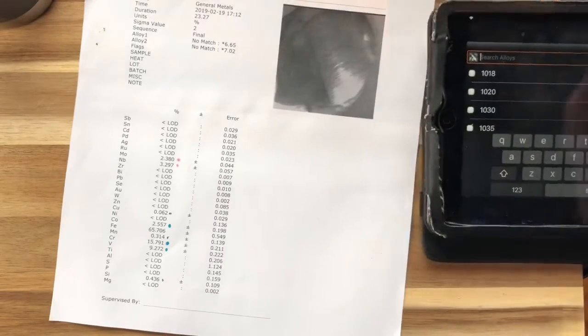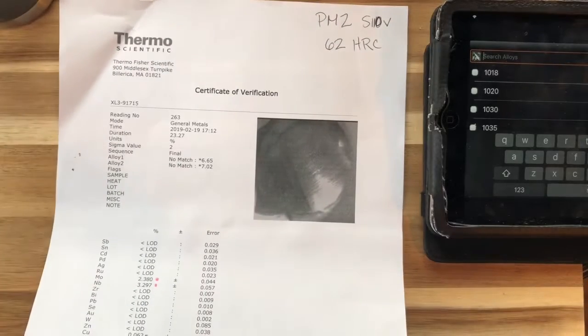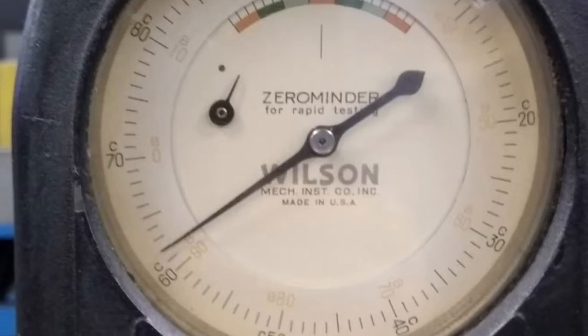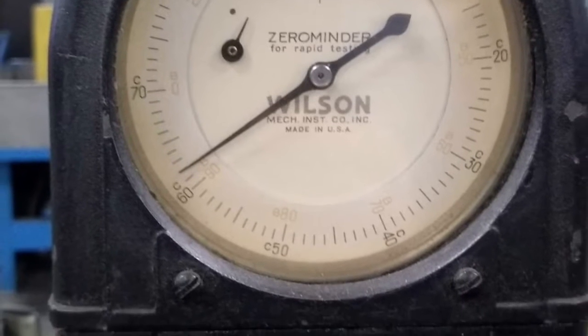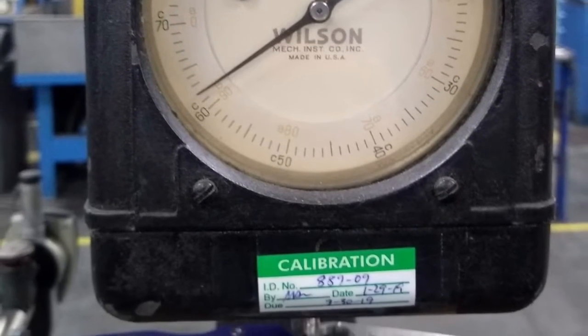And when you see that, you'll see was this knife being tested, and it was done very well by Spyderco. They did a very good job with the makeup of the steel and the way it was heat treated, because you will see by the way, so with S110V, the target by CPM, what they say is between 58 and 61, and they came up at 62, guys. I'm gonna go ahead and show the machine testing the knife, and you will see it is at 62 HRC, which is very well done, guys.